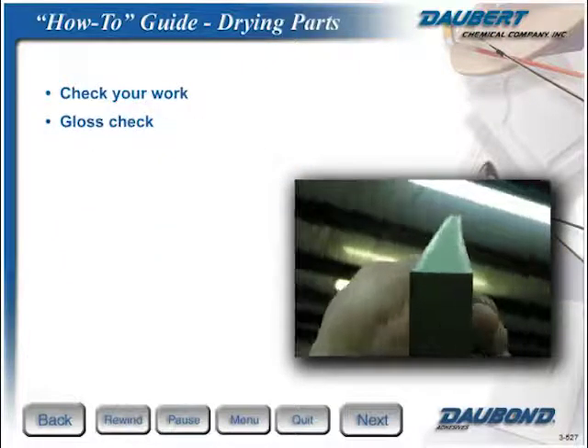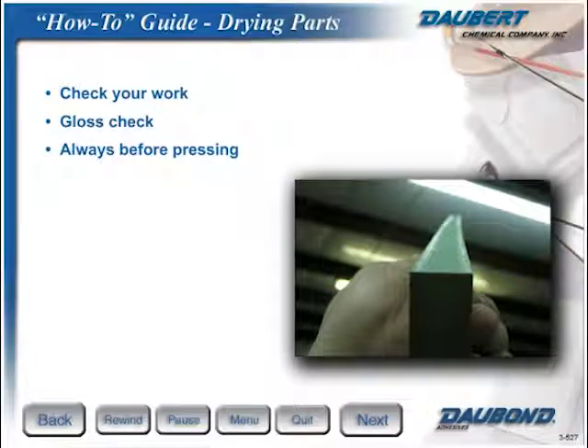If the part is glossy on the top edge and on the bottom edge, but not in the middle core, then the adhesive has soaked in too much. Always check the gloss before pressing. Look for gloss on the edges and in profiles.